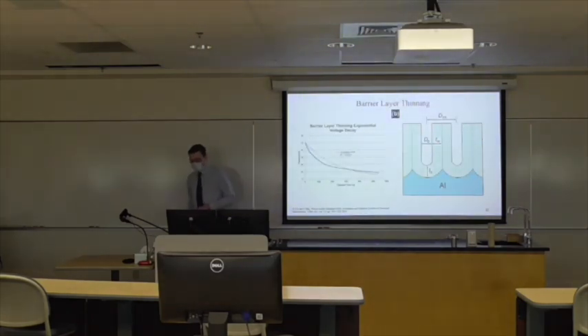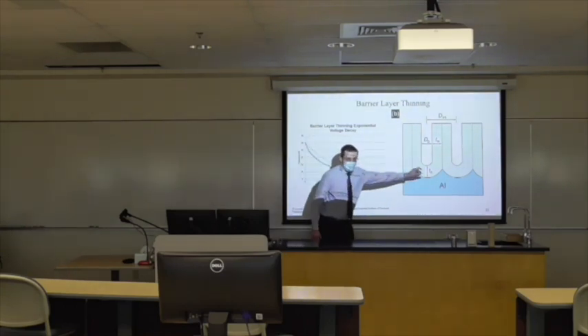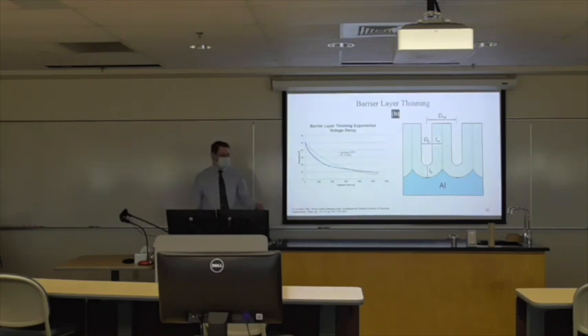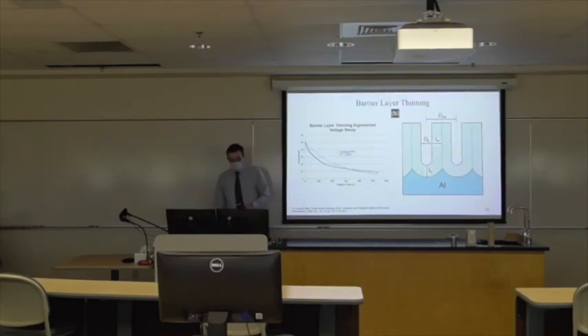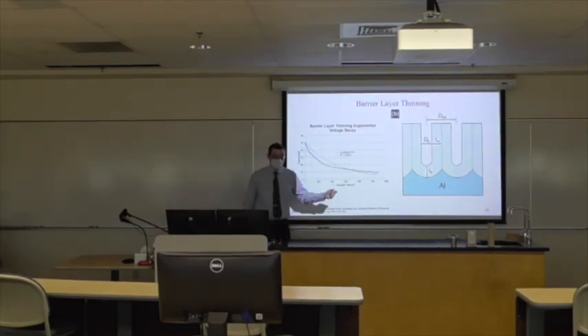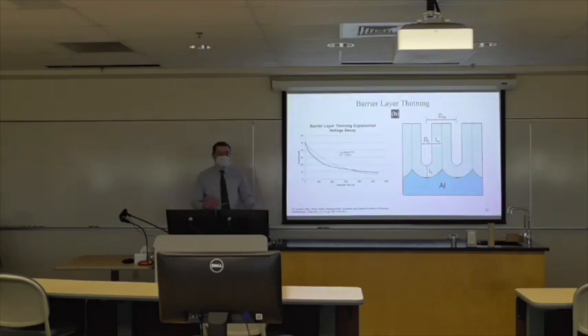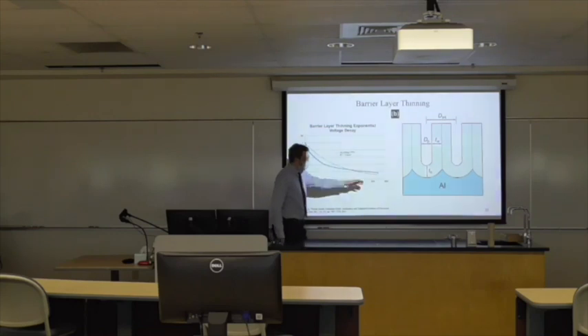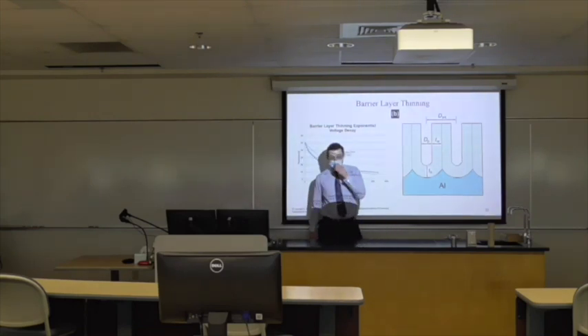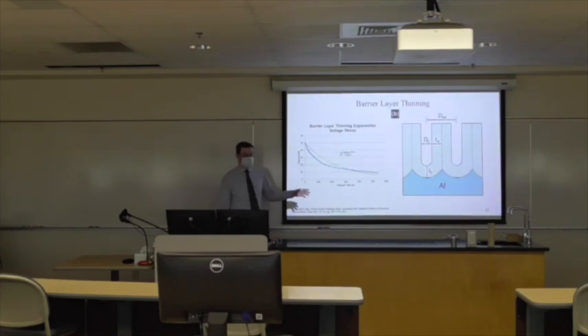One of the things that we can do here is gently lower the potential used in the anodization at the end in order to produce a thinner barrier layer, because the barrier layer thickness is directly proportional to the voltage used. So if we gently lower the voltage used, then we can get a thinner barrier layer. If that barrier layer is thin sufficiently, then although it is still an insulator, it's thin enough that current can pass through and that the aluminum that exists under it can be used as the electrode in electrochemistry.